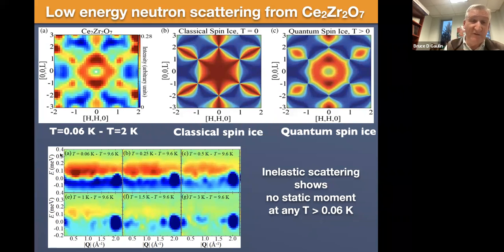Of course, there is spectral weight, which is getting enhanced as you go down in temperature, but that spectral weight is all inelastic, and it's between about zero energy and let's call it 0.2 meV. So we can take this range of energy and integrate that up for our single crystal and look at the Q dependence of this diffuse inelastic scattering.